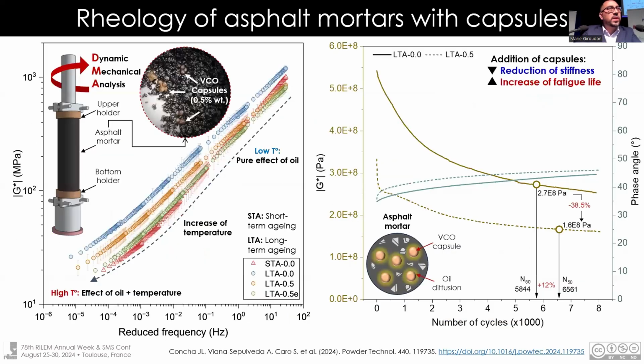Several tests use mastic. Mastic is a combination, in this case, of bitumen plus small pieces of aggregates and capsules. You can evaluate the rheology properties of the mortar, because the mortar is so important in order to evaluate the mechanical behavior of the asphalt mixture in real conditions. We can improve the properties using capsules, but you need to incorporate the exact amount of capsule, without affecting the asphalt performance.